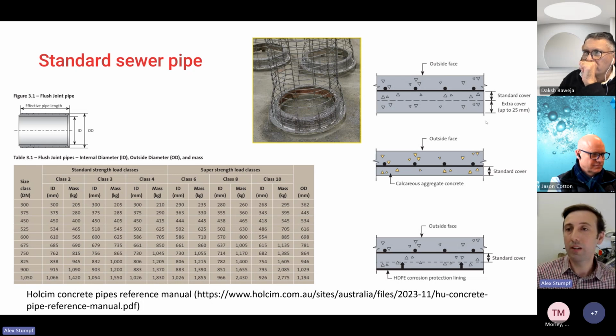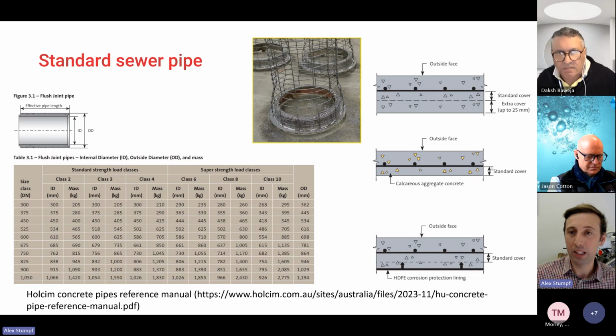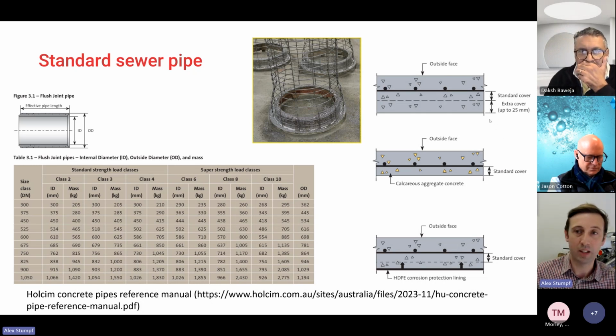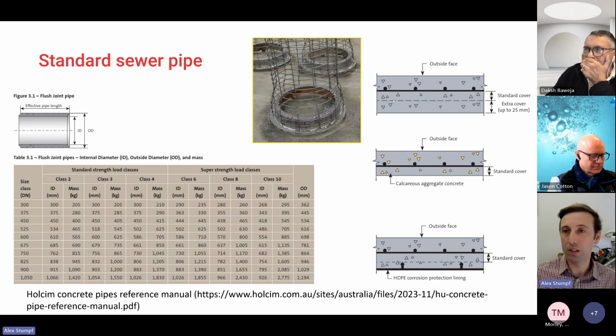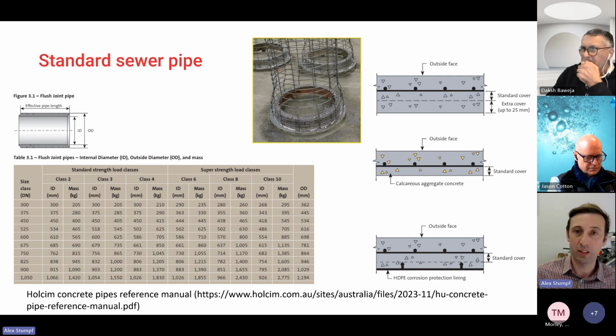Now, on the right-hand side, I've got a little bit of an image as to how we currently tackle this problem, and we simply just add in sacrificial layers, as Jason was talking about. So extra cover up to 25 mil is usually added, to ensure that we don't impact the structural integrity of the pipe, but we also want to make sure that we don't expose the rebar. As soon as the rebar is exposed, that's a pretty critical issue that we must deal with. So that's why we add material to the inside of the pipe.